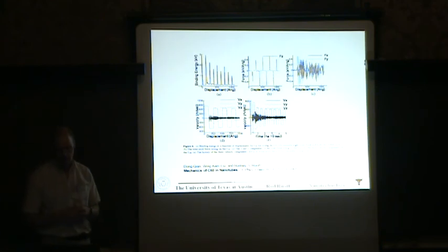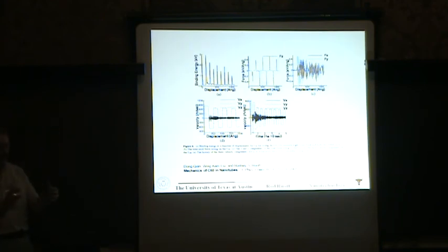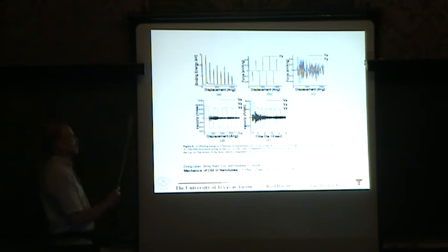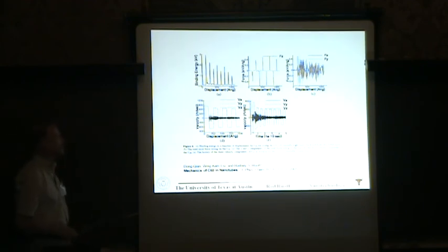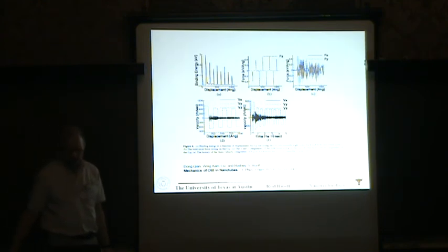And so this shows that what happens when you have a C60 on the outside of the tube is it gets sucked in just like a straw, and then it zips back and forth. So what's happening is it goes out the other end, actually projects out the other end, and then gets sucked back in, and that goes back and forth for a very long time. Actually, you can't typically calculate for a 10-10 tube of the length that Dong chose when it actually stops, because the calculation would run for too long.